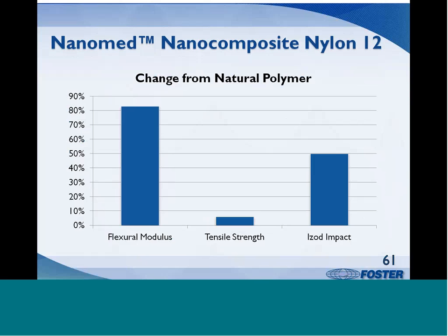This illustrates how platelets can affect the physical property mix. The flat, square morphology of the nanoclay appears to most readily enhance flexural modulus and izod impact strength. Without a significant aspect ratio and isotropy, the platelets are not as efficient in modifying tensile strength. A fibrous nano reinforcement, such as halloysite or palygorskite, with an easily identified length to diameter aspect ratio, would be expected to have more of a positive effect on tensile strength.